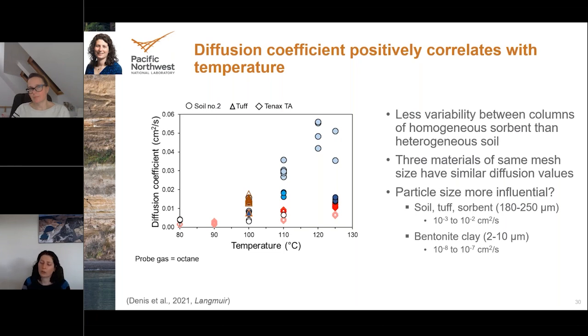So for us, for many of the materials, we either worked with powders or sieved materials. And for the sieved materials, we would try to get at least a window, like the 60-80 mesh, which is equivalent to 180 to 250 microns. So the sample prep usually isn't too difficult unless you have a material that clumps together. Then that particle size might not be reflective, as if you have a really powdery material, you could try to sieve it and that's not really particle size. It's just how the material is clumping together in different pieces.